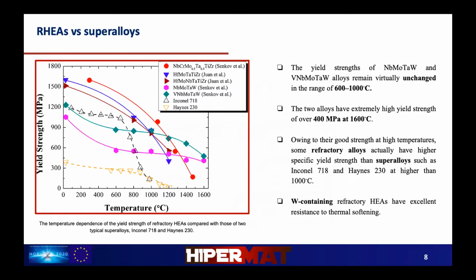Now some comparison of refractory high entropy alloy and superalloy. On the left side, we can see a graph for yield strength versus temperature. The solid geometries here refer to the refractory high entropy alloys, whereas hollow geometry refers to the Inconel and Haynes 230 superalloys. So if we consider the graph here, we can see the yield strength of the green and purple